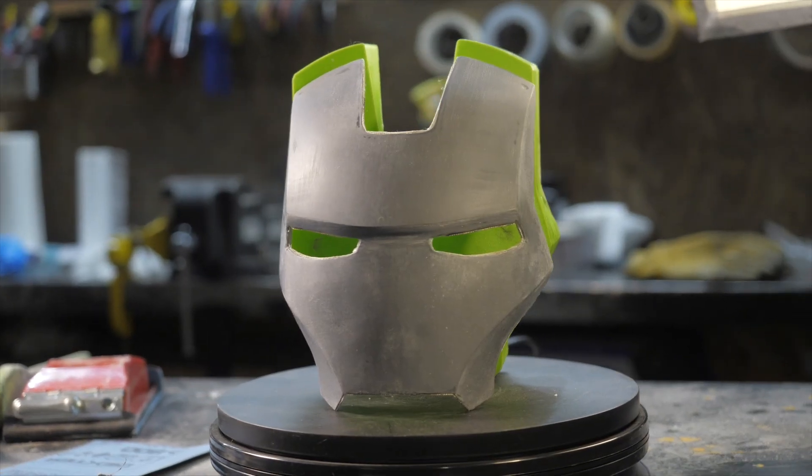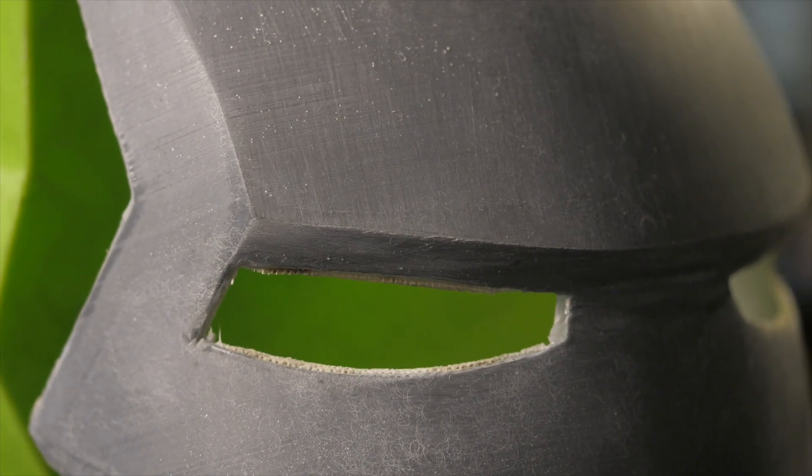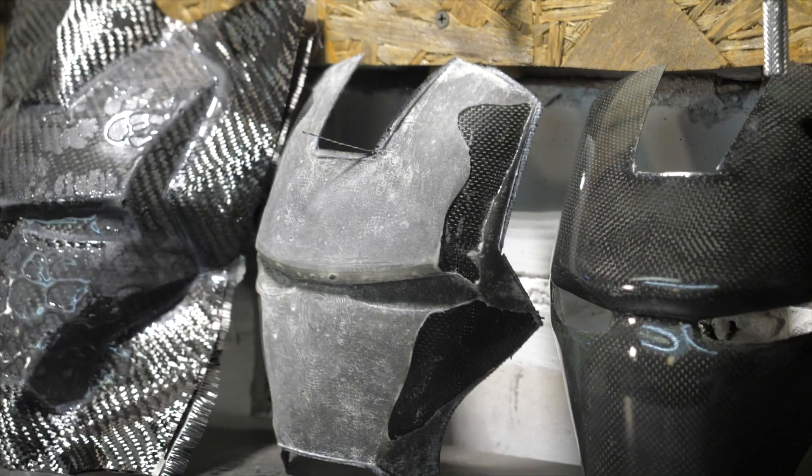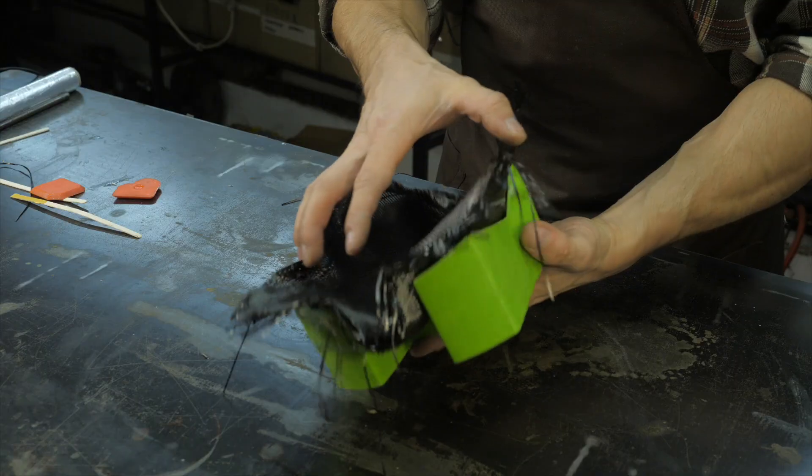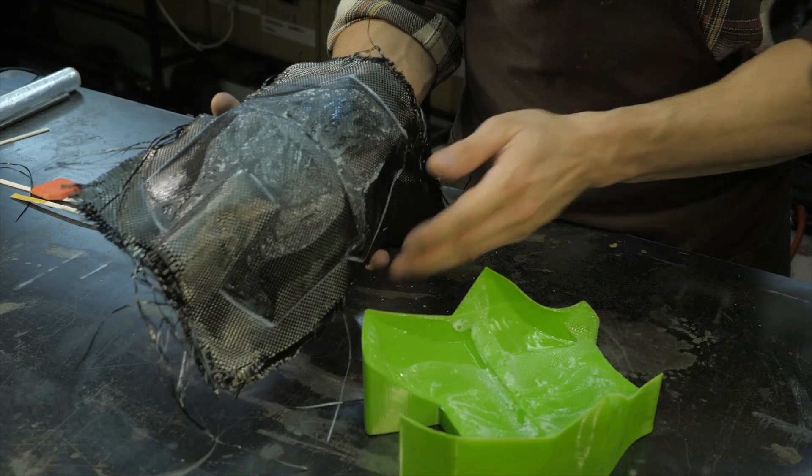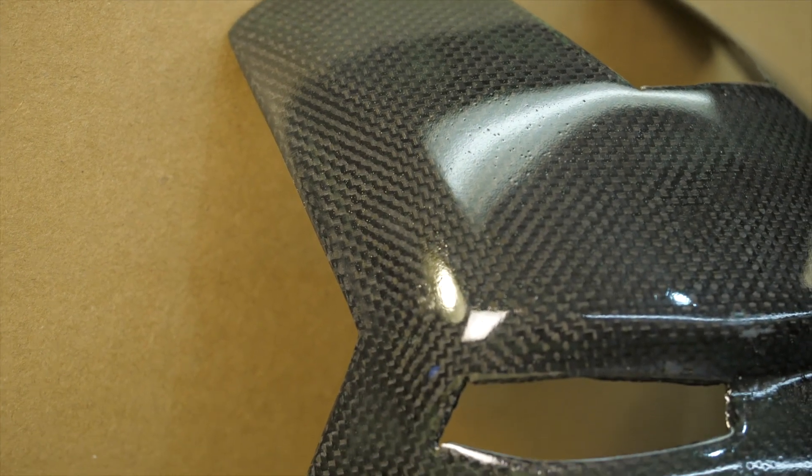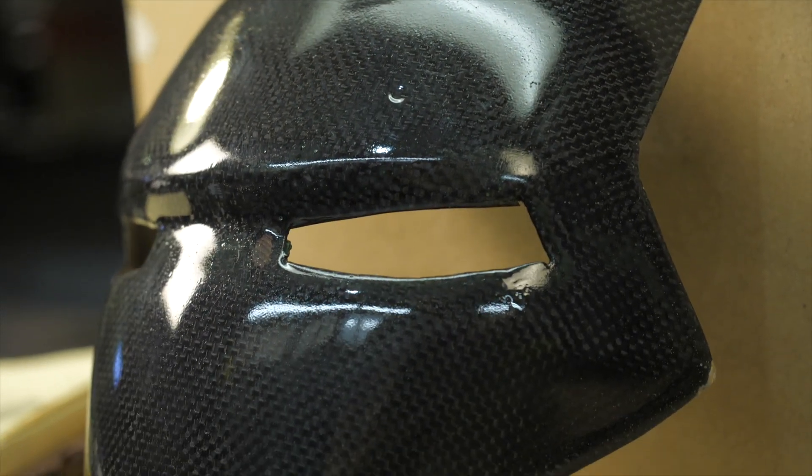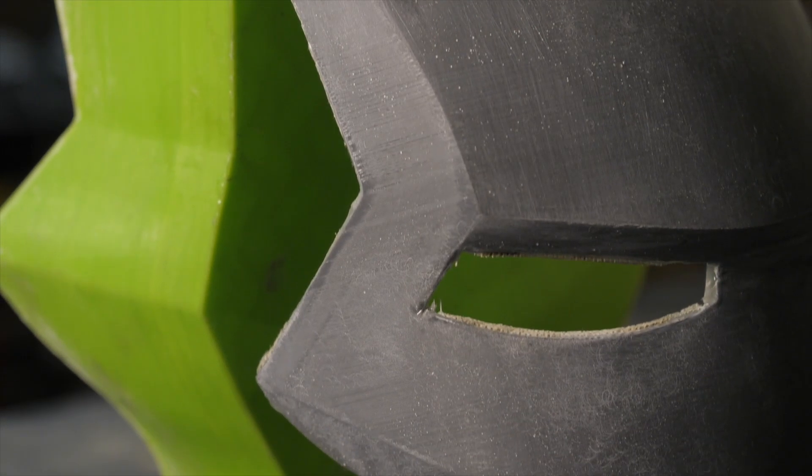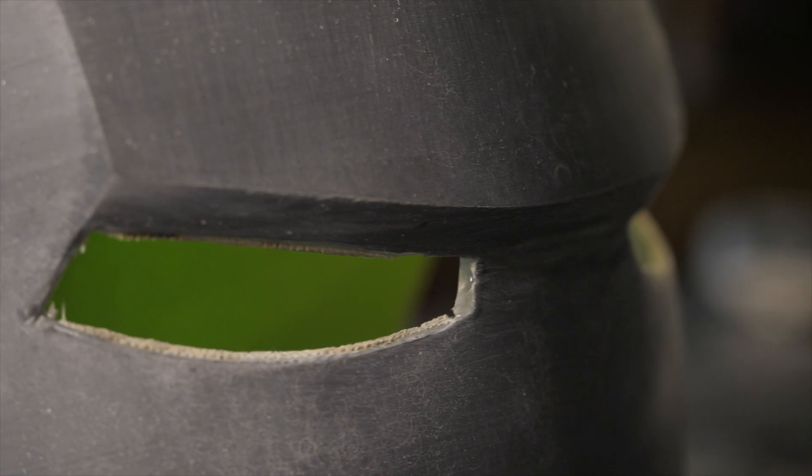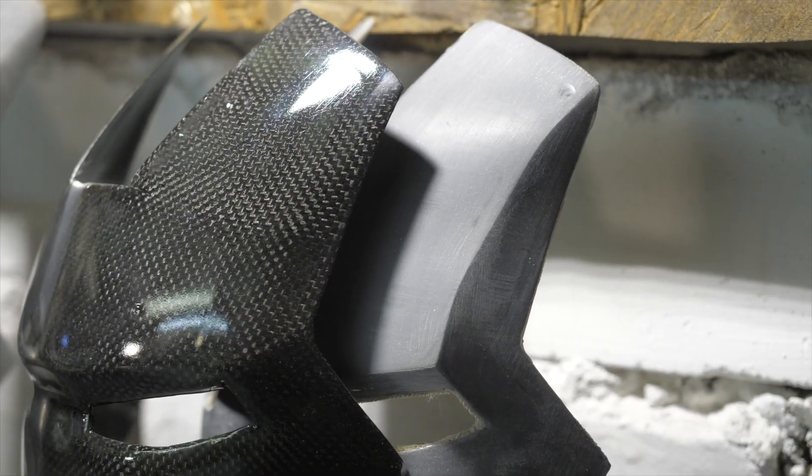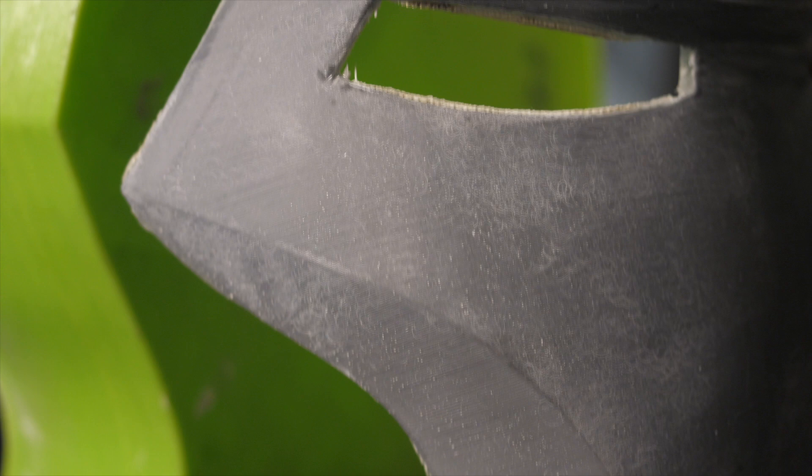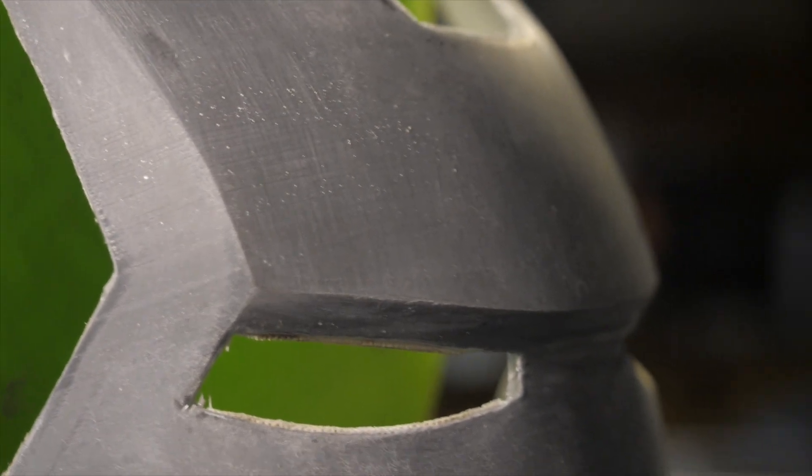The third and most important advantage, this is the quality of the front surface and high detail. In the mold technology, the front layer of the part is formed at a secondary cast from the form and even when selecting the best components, it loses some of the details and the corners and edges are quite smooth. In a new moldless technology, the front layer is formed not by the imprint from the mold, but that primary part printed on a 3D printer and saves maximum detail and sharpness of the edges and corners.